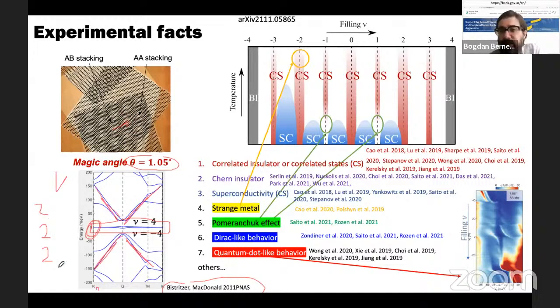But these 8 bands can, of course, in single particle theory, be occupied by 8 electrons, which will count from -4 to 4. And counting from -4 to 4 means that we can basically gate tune this system, now being that this has much lower density because it's much larger in itself, so you can gate tune it much more easily than normal graphene. You can gate tune the system from the single particle gap, which sits here, which is at filling -4, to the next single particle gap, which sits here, which is at filling 4.